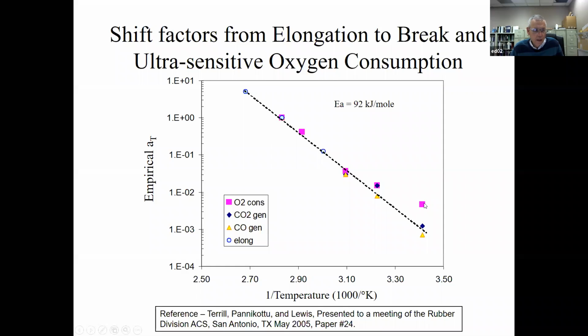And this has been published for other elastomer systems, butyl rubber, and NBR, chloroprene. This is the work of Ken Gillen at Sandia National Laboratories. Sandia National Laboratories developed the ultrasensitive oxygen consumption technique to enable them to better predict service life of military things. And my understanding is that the service life is often governed by an O-ring seal in military missiles. So it's very important to know how long it's safe to store those things.